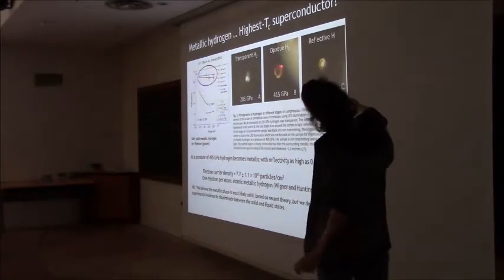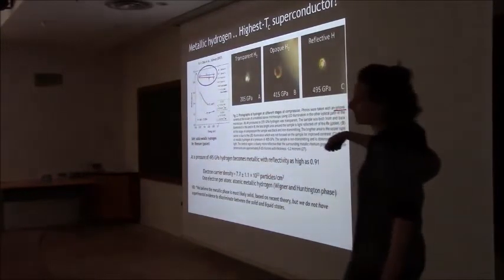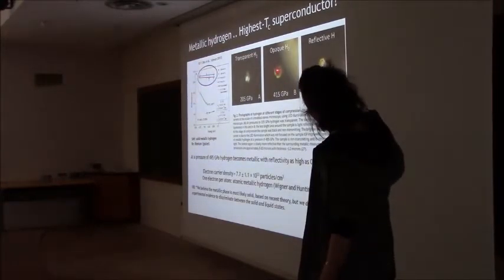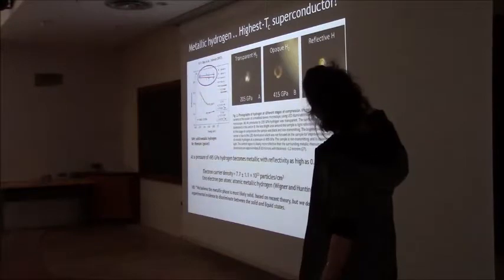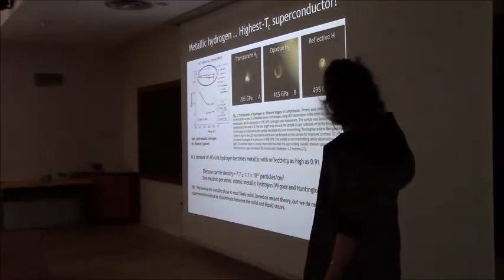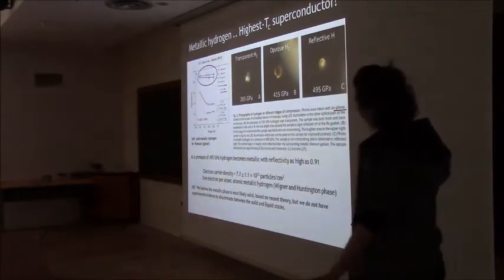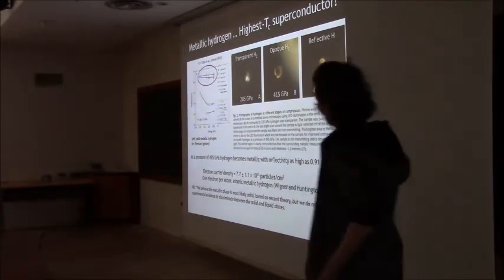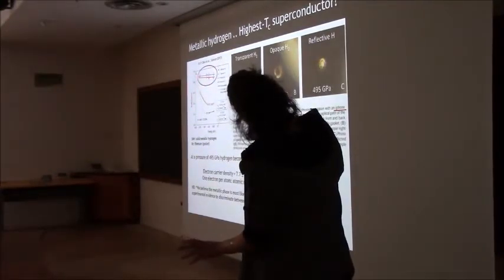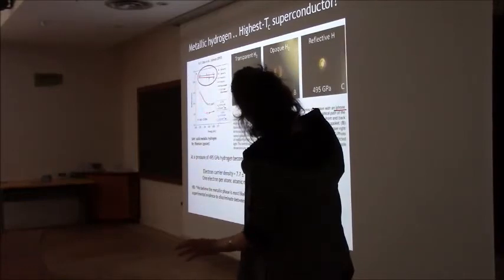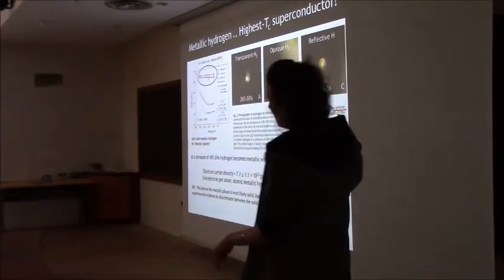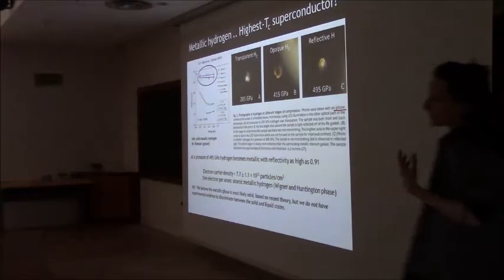So what you see, the ring here is the gasket, the rhenium gasket, and this is the hydrogen. And then when they apply almost 500 GPa, they get some reflectivity. The fun thing is that they took a picture with their iPhone and they say it in the paper. So it doesn't look serious, but I think it's serious. And for the proper measurement, they measure the reflectance of the hydrogen and the reflectance of the gasket. And clearly here, when you have a reflectance of almost 0.9, you know that you have a metal.